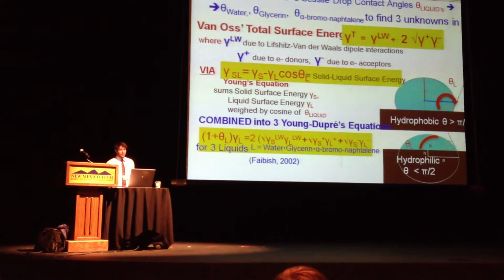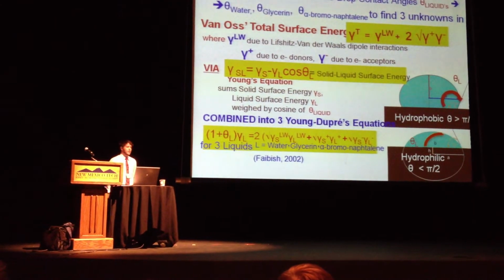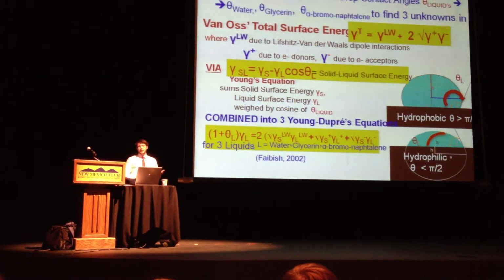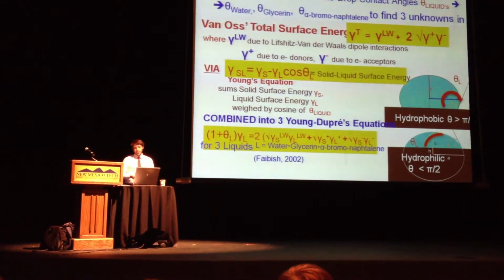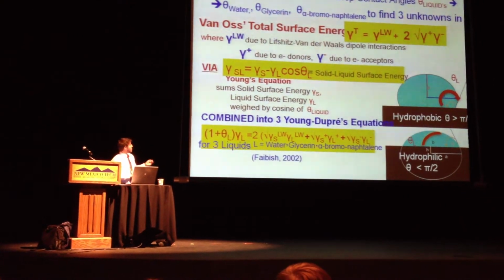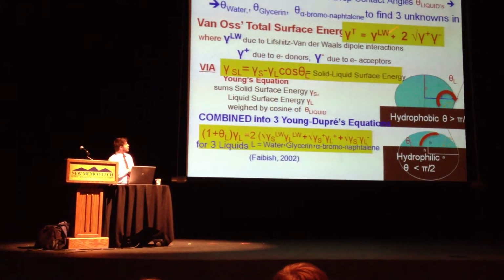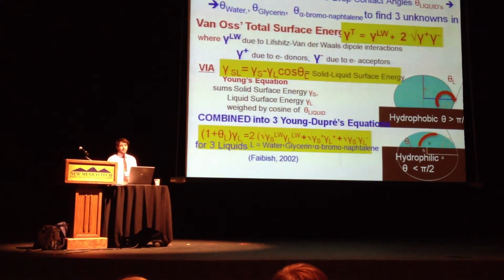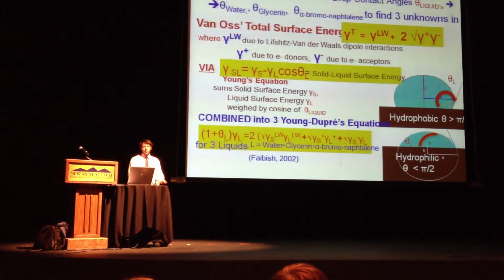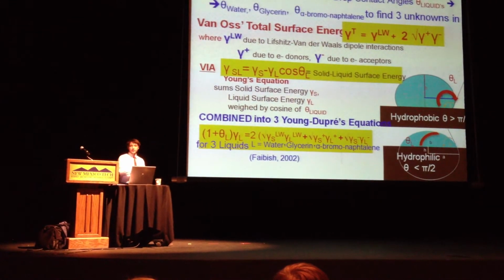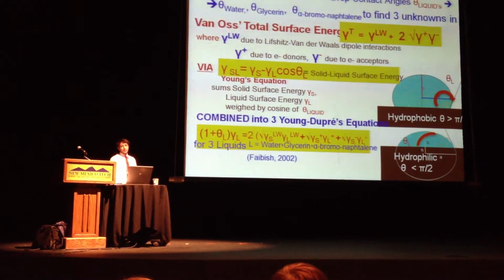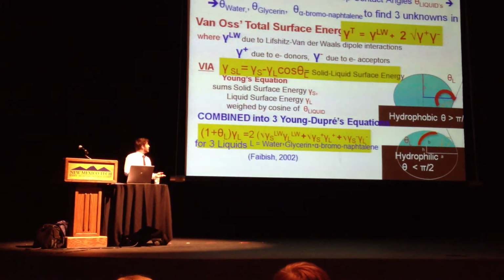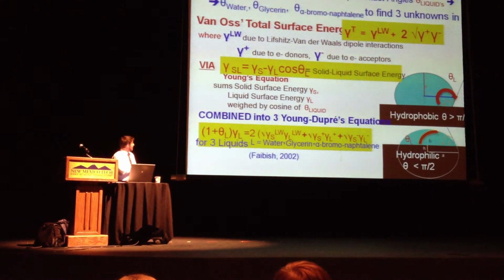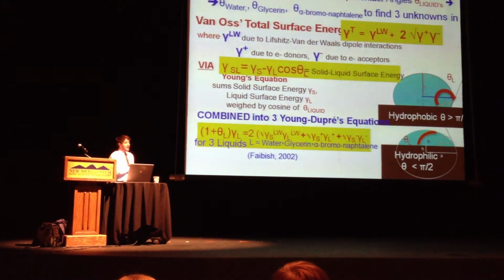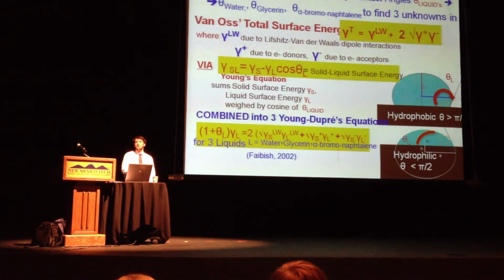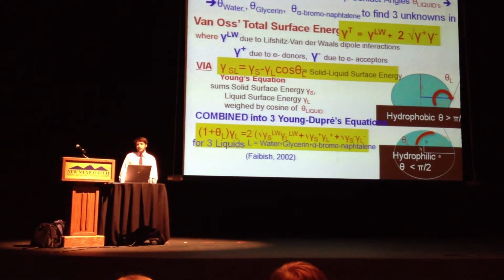These equations sort of go over the theory of what's going on. We measure an angle of our liquids on the surface, using 3 different liquids that are intended to pinpoint which portion of the surface energy, either the van der Waals or the donor-acceptor portion of the free energy. We use 3 liquids to create 3 equations, 3 unknowns that will give us the information needed to determine the surface free energy of our sample. So combined, we have these equations that relate the angle of our liquids to some known values for the liquid, and then our unknowns of the surface free energy.